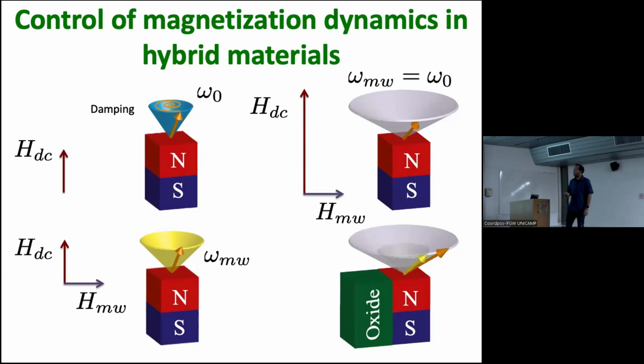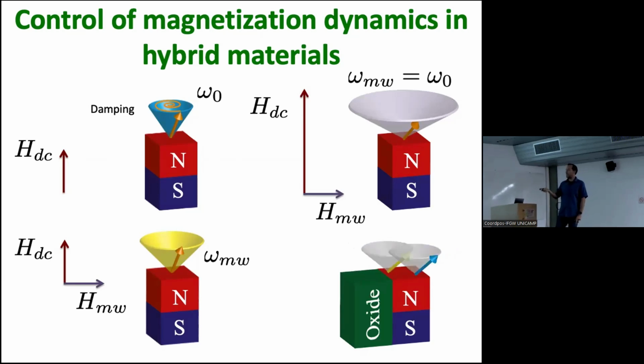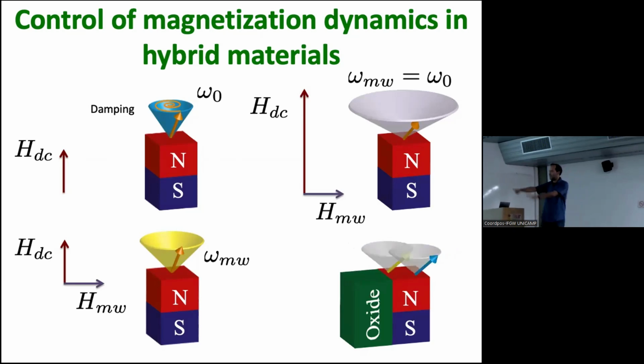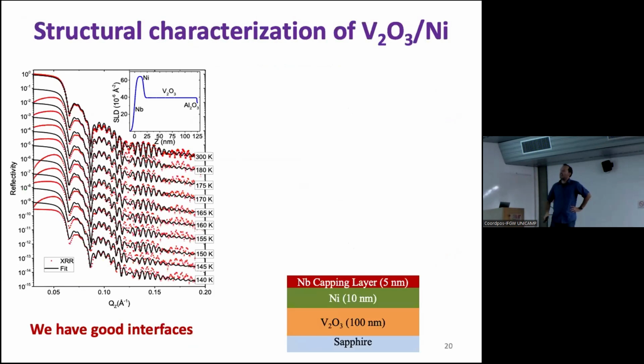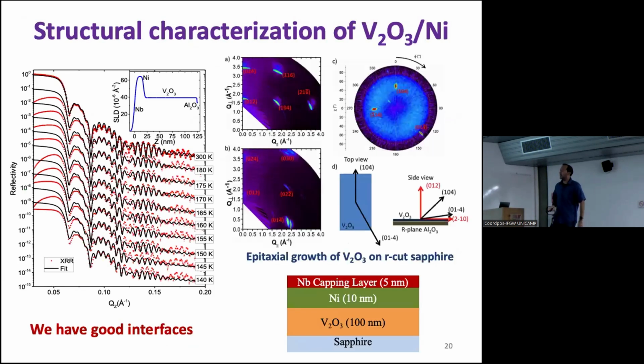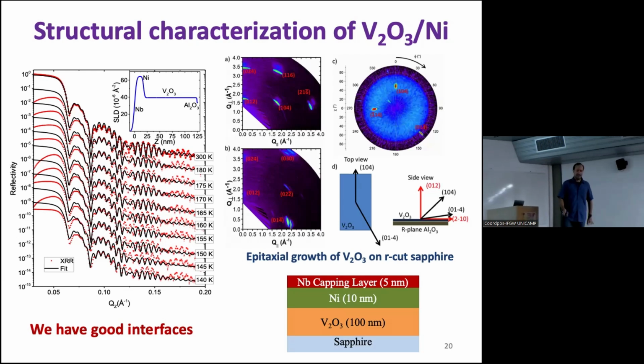Okay? What we found is that actually there appears to be two resonances, something like this, I will show. And this was kind of a novel discovery, very interesting and very useful as well. Okay, so this is just technical, I'm going to skip it, basically just to show you that these interfaces are good. We don't have much roughness between the layers. So whatever I'm going to show you, we cannot blame on the samples not being good. That's kind of the bottom line.